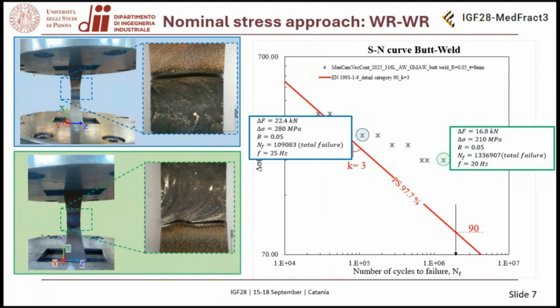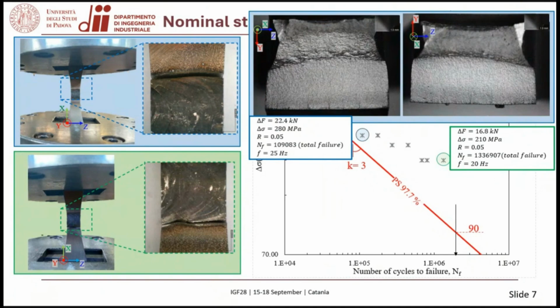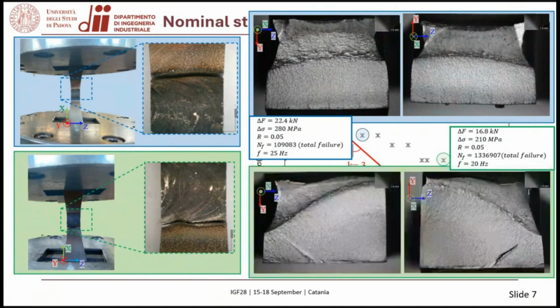And the same, we observe in a joint tested in a low-level condition. We observe also in this case failure at the weld toe and the propagation along it. Focusing on the fracture surface, we observe in the high-level test specimen multiple fatigue crack initiation points, almost equally distributed along the specimen thickness, and finally the plastic zone due to static failure. Focusing on the fracture surface of a low-level test specimen, we observe the main fracture initiation point from this side, and only probably a secondary starting point in this zone.